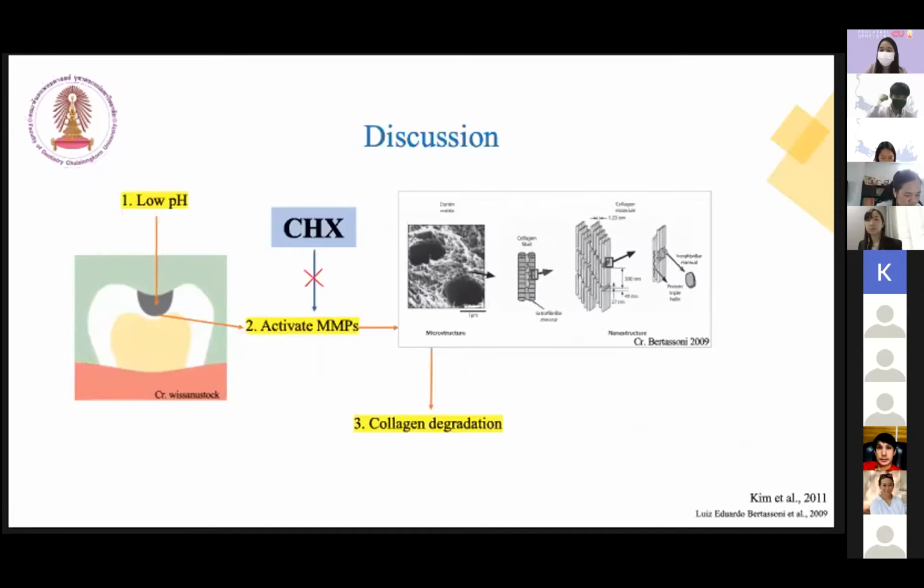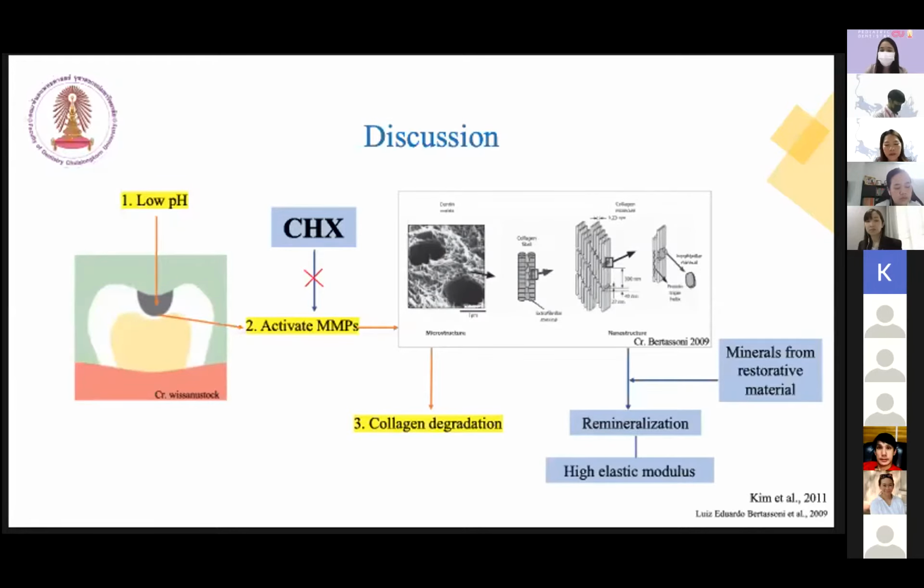from collagen degradation. Collagen fibrils are surrounded by extrafibrillar mineral, intrafibrillar mineral, and protein triple helix. They give collagen fibrils elastic behavior and resistance to demineralization. Intra- and extrafibrillar minerals also have mechanical recovery themselves, though dentin is partially demineralized. When collagen fibrils are reincorporated with minerals, remineralization is promoted again.